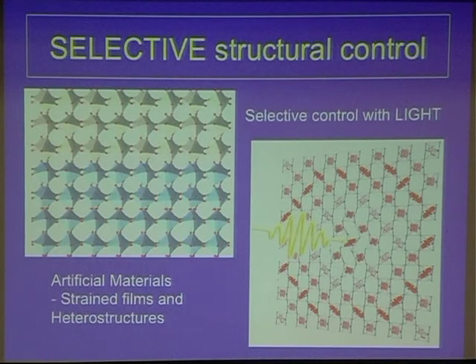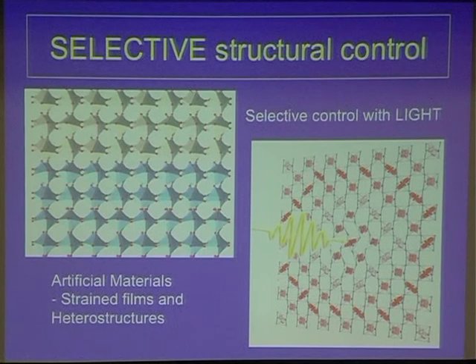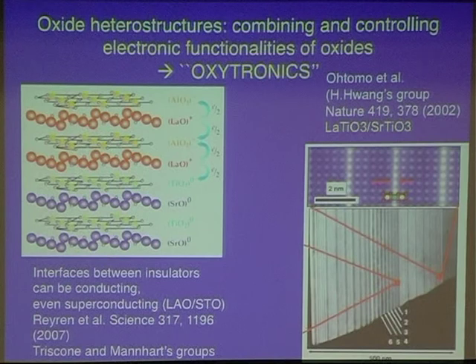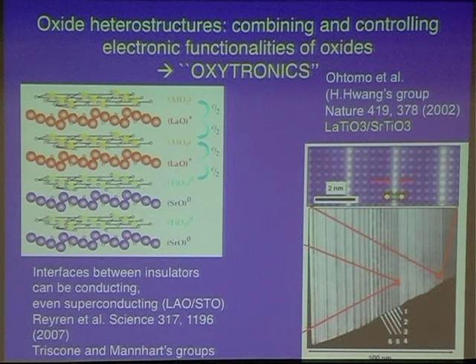Another route, which has been really pioneered by Andrea Cavalleri in particular, is to do selective excitation, selective control of the structure with dedicated lasers which can excite specific structural modes in a resonant manner. So let me elaborate a little bit more on these two directions. Using techniques for growing materials like molecular beam epitaxy, one can actually grow these oxides layer by layer, forming materials that do not exist in nature, but that are nevertheless perfectly stable, in which we can combine the functionalities of different oxides and induce interfacial strains and so on.